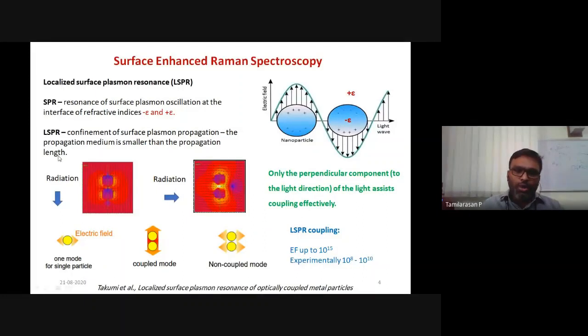Okay, you have taken a metallic particle and you have reduced its size to nanoparticle size, say smaller than its SPR propagation length, and you have illuminated it with light. So now it produced LSPR on its surface and it produced a large electric field. What if you put two particles together, adjacent to each other? Then there will be another phenomenon called LSPR coupling. These two LSPRs of the particles will couple together and form an enhanced electric field region of nanometer cube size. So the region between the two particles will have a very high field enhancement. If you calculate this theoretically, it goes up to 10 power 15, and experimentally people have observed 10 power 8 to 10 power 10 times the enhancement factor.